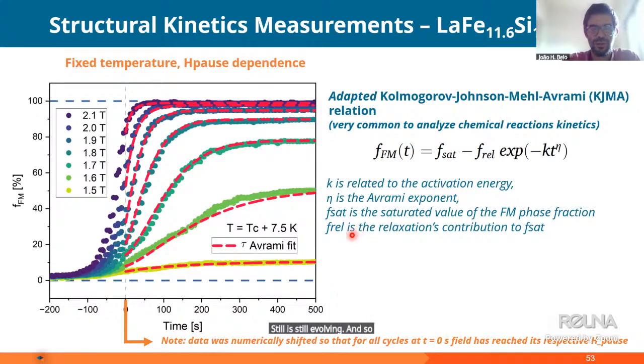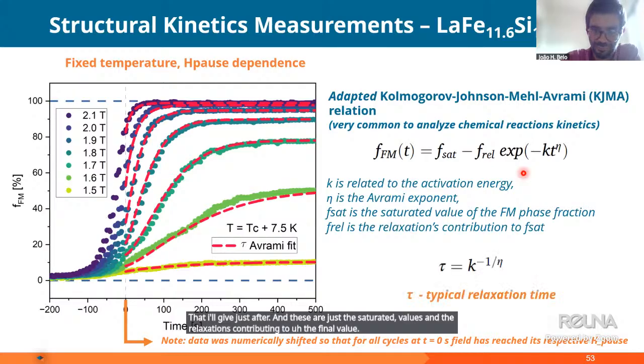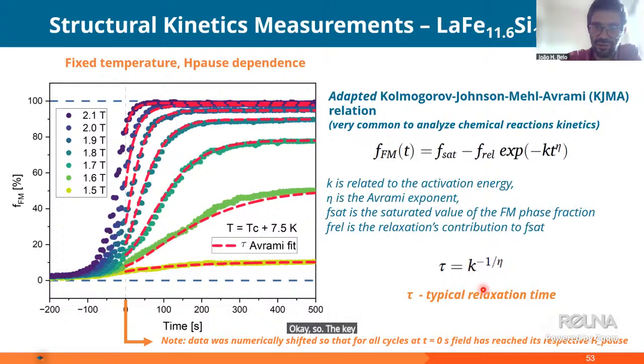And so by looking at the literature and studying, we decided to apply this KJMA model, based on the Avrami modeling of chemical reactions and phase transitions in general. And we applied this model to fit this data, where this parameter, K, is related to the activation energy required for the phase transition. Eta is called the Avrami exponent, associated with a further physical meaning that I'll give just after. And these are just the saturated values and the relaxations contributing to the final value. Okay, so the K value and the eta allow us to take the typical relaxation time, so how long the transition takes to occur.